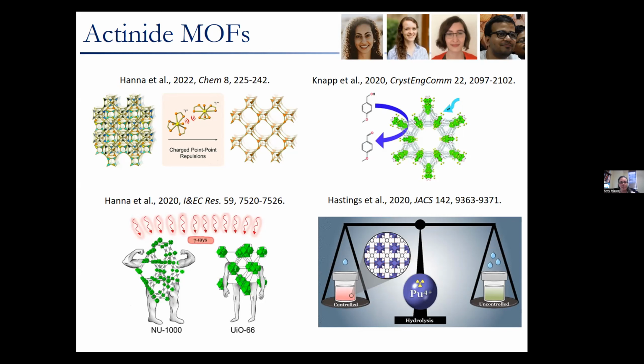And then finally, over on the lower left-hand quadrant of the slide, represents our first steps at studying the radiation stability of these MOFs. So in this paper, Sylvia compared the radiation stability of NU1000 and UIO66. So again, these are both zirconium-based MOFs, but they have different linkers and different topologies. So she studied them both at a low gamma ray dose and a high gamma ray dose. I think the low was like one gray dose, and the high was, I want to say 14 grays or something like that.